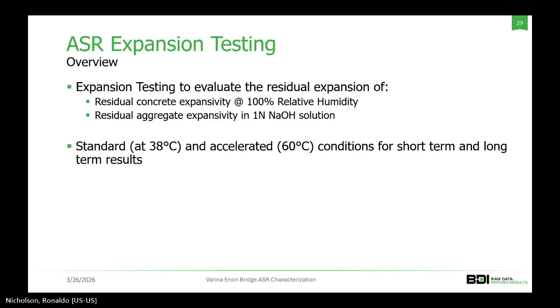In this case, we did two different environmental conditions, so one at 100% relative humidity and one in sodium hydroxide solution. And we did this both the standard and accelerated testing, one at 38 degrees C and the other one at 60 degrees C. Next slide, please.